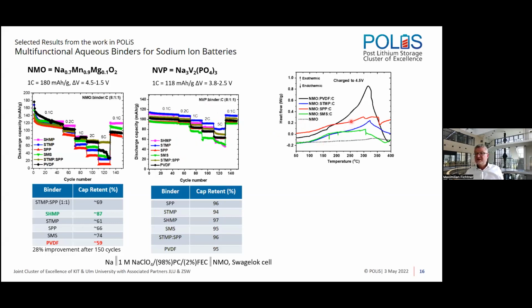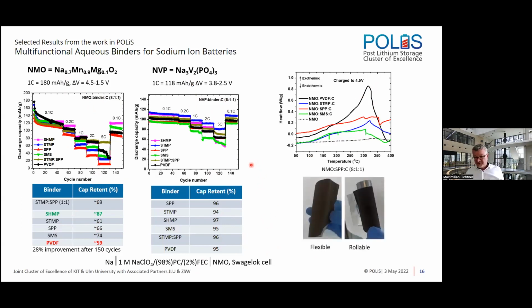You see here again, this is the electrode prepared with PVDF as a binder, and this is the electrode prepared with the inorganic binders, so you do not see a strong exothermic trace here. Eventually, a couple of things improved: the processability, but also the capacity retention was improved, especially here of this layered system, which is a little bit of a critical thing because this is prone to degradation. Here it's more stable, but also here you see an improvement when you take this particular binder, and also the mechanical properties are quite good. This can lead to a flexible coating, and you can even roll it, and so everything remains stable and nothing is detached.